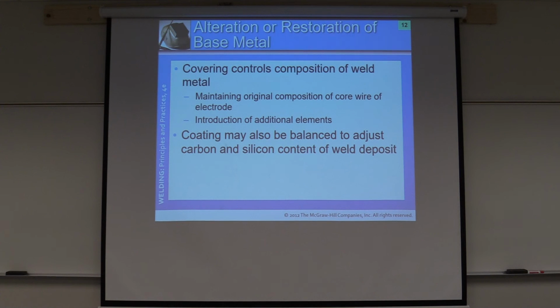So we kind of talked about that in chapter 11 a little bit. I said we'd get into it a little further as we're going along. Let me finish this paragraph and then we'll talk about it. Low hydrogen electrodes greatly improve the welding of high carbon and alloy steels, high sulfur steels, and phosphorus bearing steels. Such steels tend to be porous and crack under the bead. The reduction of the hydrogen content in the weld eliminates these harmful characteristics. Okay, let's take a break and we'll go to the PowerPoint.